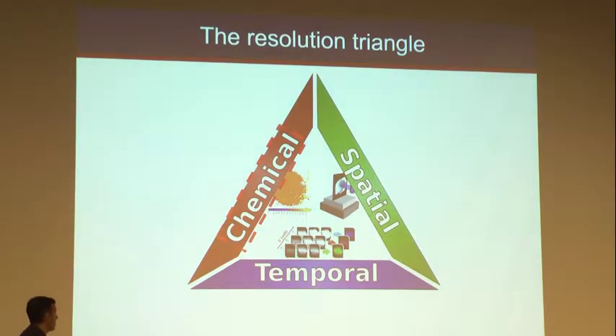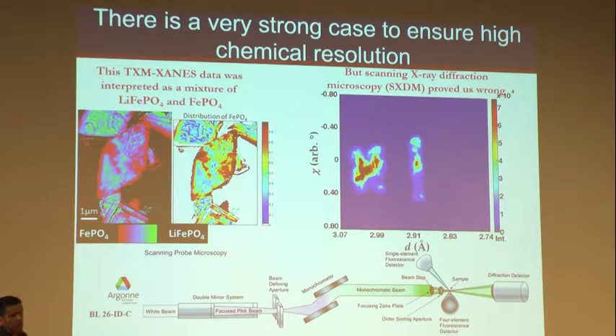Okay, so I've made a case for spatial resolution. This is something that those of you working in microscopy have worried about. The next area that I want to address is chemical resolution, because I will confess that this was something that made us look a little bad, but I'm still going to show you the data. On the left is the original type of particles that I showed, the first chemical image, those 4-micron particles in a full-field TXM microscope at the K edge of iron. What we truly get in those measurements is an X-ray absorption spectrum of the iron, so we're able to tell how much iron 2 and iron 3 there is.